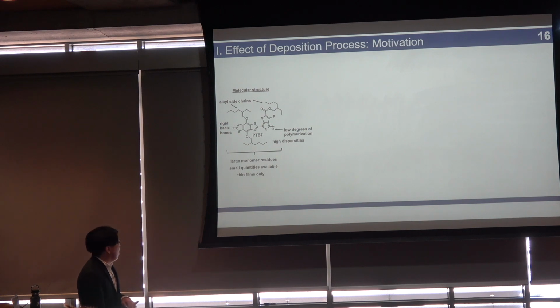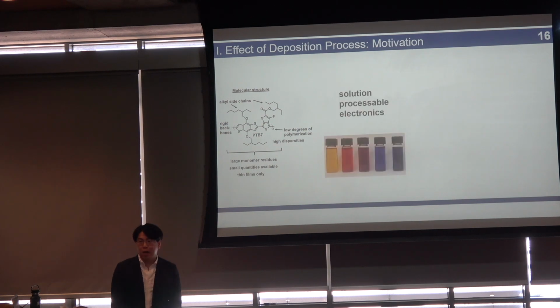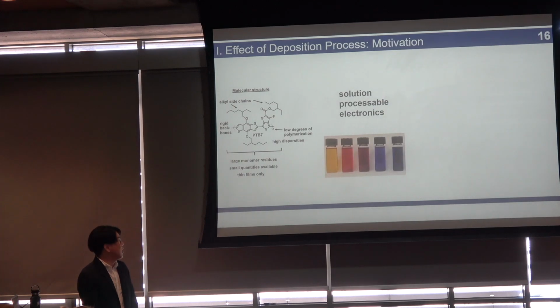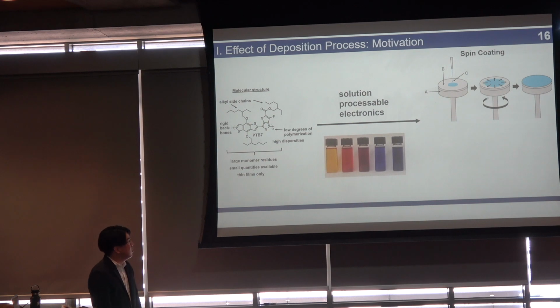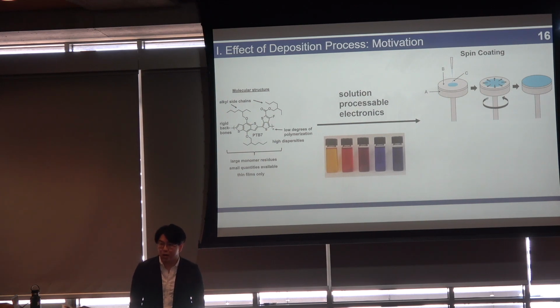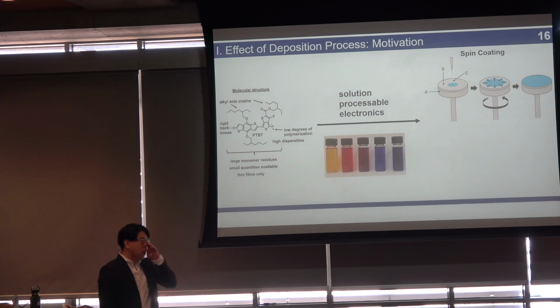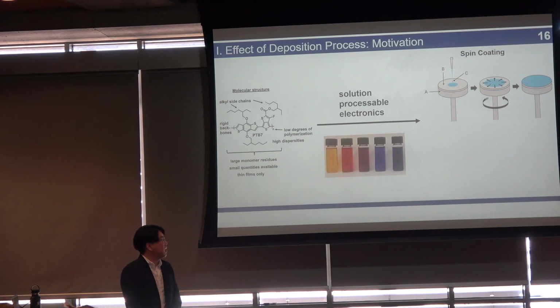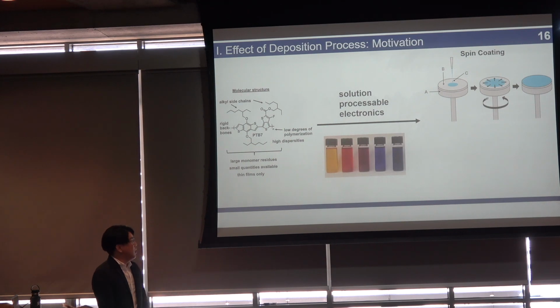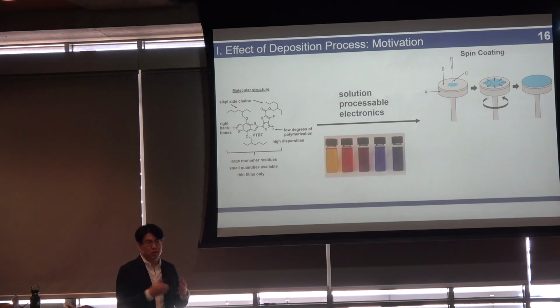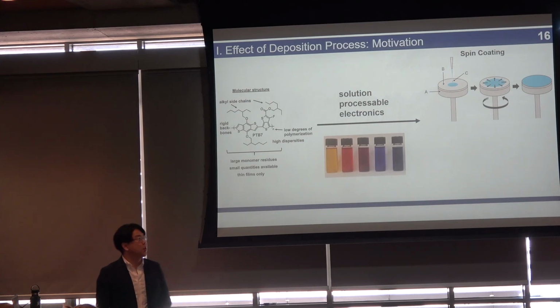So for semiconducting polymers, the nice thing about this is we can actually process these at room temperature from solution. So these are solution processable electronics, and generally we do these by spin coating. So we deposit films by spin coating at the laboratory scale. What this means is we put some polymer solution on top of a substrate of some sort, and we spin it really fast, and this creates a uniform film.